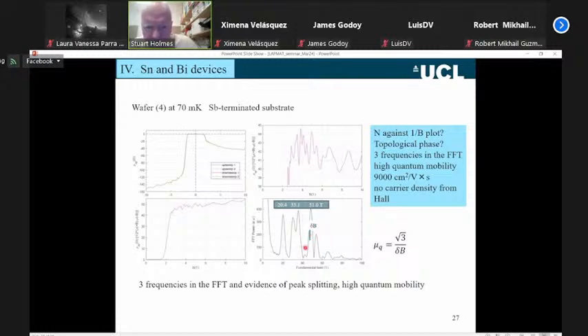We have a second peak, so we have 3 peaks. We have 3 peaks in this system, 2 of which are topological, and they are also split. We also have this bulk peak here, which is not split. There's no spin splitting in the bulk, and there's no topological behavior.